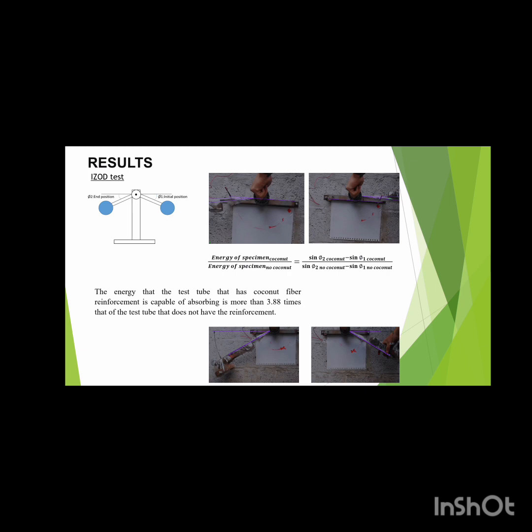The section in which the material fractured was in completely different areas for the specimen that is reinforced with coconut fiber. This began its failure from the point of impact, very vertically to the embedment, following a line of failures of the material, a product of impurities in the coconut fiber, which can be seen in the image beside the test tube. Unlike the material with reinforcement, the epoxy resin test tube did not present defects in its structure, but the rupture was parallel to the ground right in the area of the embedment, which allows us to verify that this test tube is fragile.